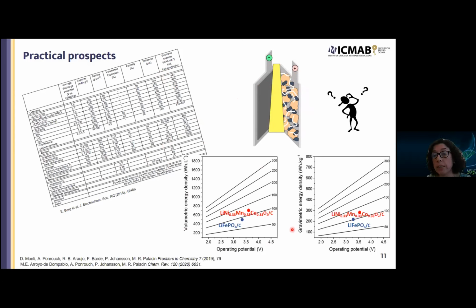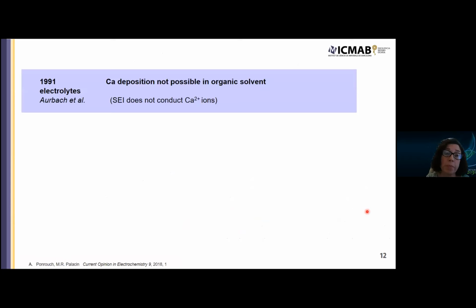This is the volumetric energy density or the gravimetric energy density considering calcium and hypothetical positive electrode materials with operating voltages between 2 and 4.5 and capacities between 50 and 300. And you see that for cathodes with moderate, I would say, figures of merit, we could be already on par with the lithium-ion battery technology. So the prospects of good performance are real. But unfortunately, the reports in the literature were not that promising.